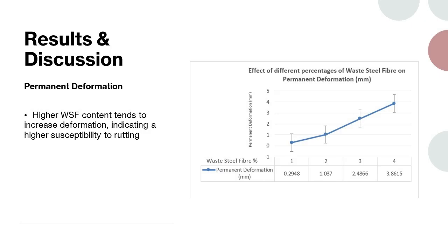The permanent deformation value indicates the extent of deformation or rutting in asphalt mixture under applied load. Higher values of permanent deformation indicate susceptibility to rutting and reduced resistance to long-term deformation. It can be observed that as the WSF content increases, the permanent deformation also tends to increase. The asphalt mixture with 0% WSF exhibits the lowest permanent deformation value, indicating relatively better resistance to rutting. On the other hand, the samples with WSF content of 1%, 2%, and 3% show higher permanent deformation values. These larger deformation values suggest that asphalt mixtures with higher WSF contents are more prone to rutting and exhibit reduced resistance to long-term deformation.